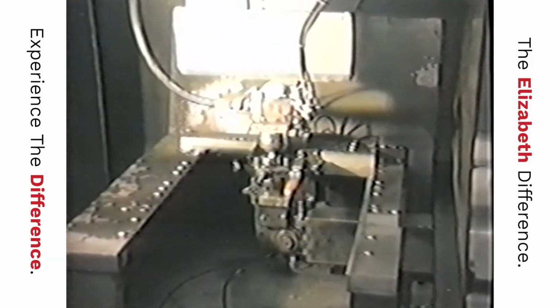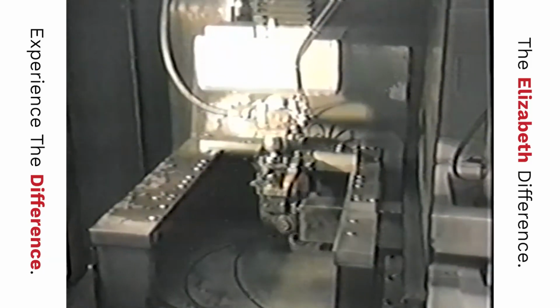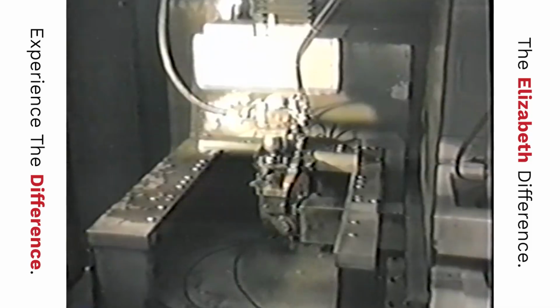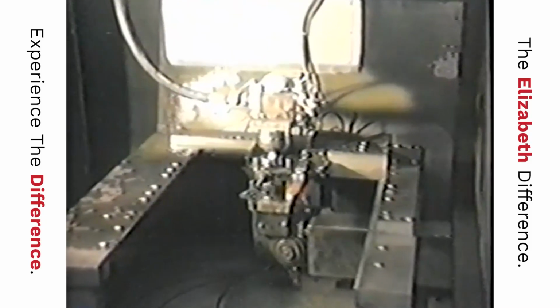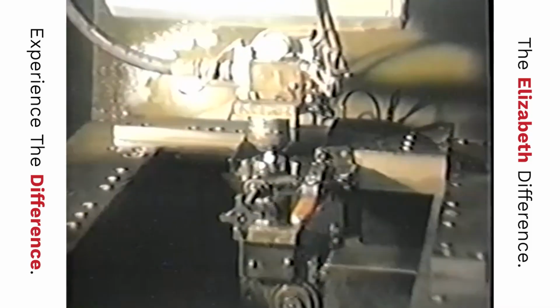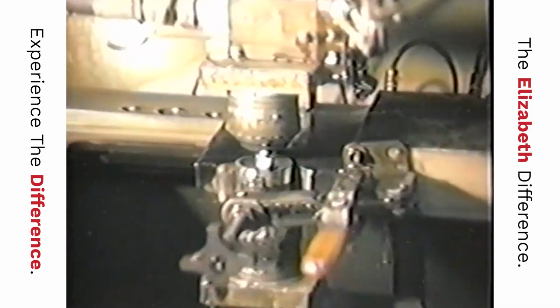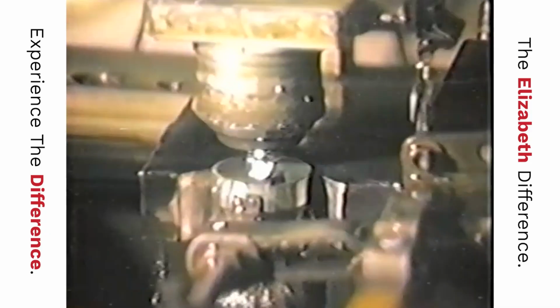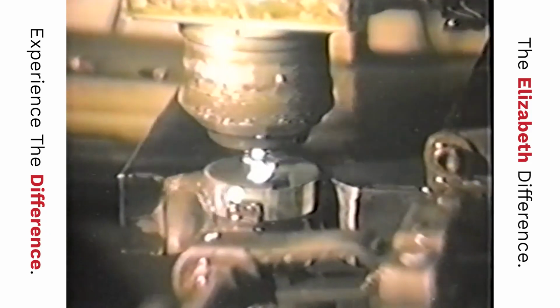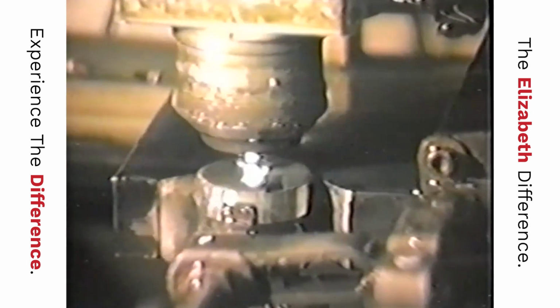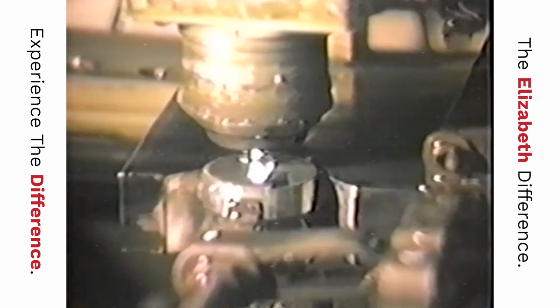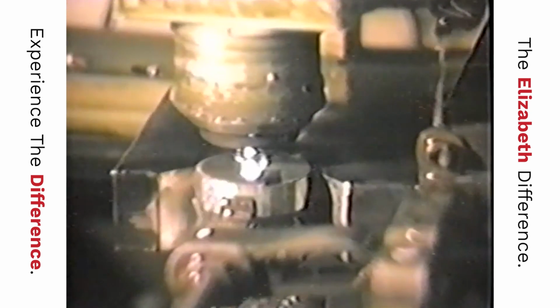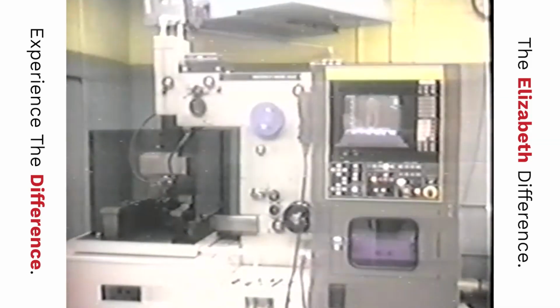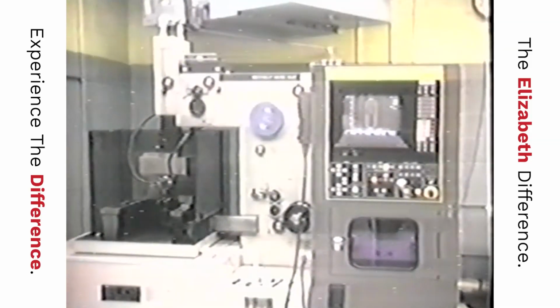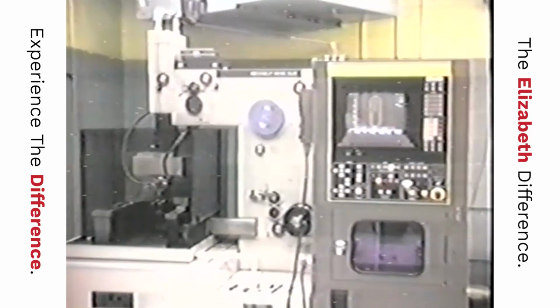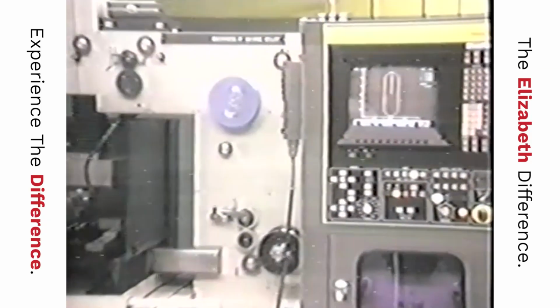The die blank is placed in the machine and the brass wire threaded through a small starting hole in the blank die. With the computer program loaded, the machine is now ready to begin the cutting process. The machine cuts by emitting very small electrical sparks that erode the metal away. The waste material is flushed away by the use of deionized water. The computer controls the path of the cut, the die ID size, and the surface finish that's required.